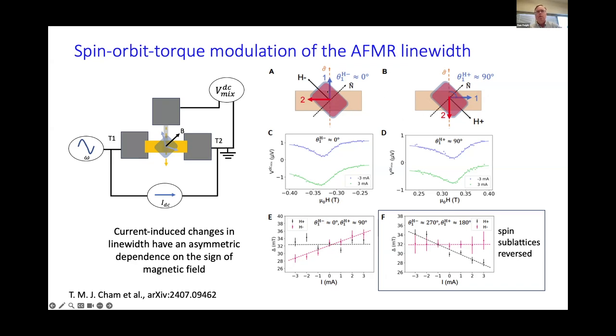For one orientation of the magnetic field, for a particular value of field, we can generate that spin parallel to the spin orbit torque. That's the situation where we see a strong dependence of the line width on the current. For the opposite direction of magnetic field, we turn the spin sublattice of the other lattice parallel to the spin axis of the spin orbit torque. But the spin sublattice adjacent to the bottom channel turns perpendicular. For that, we see essentially no effect of the spin orbit torque on the line width.